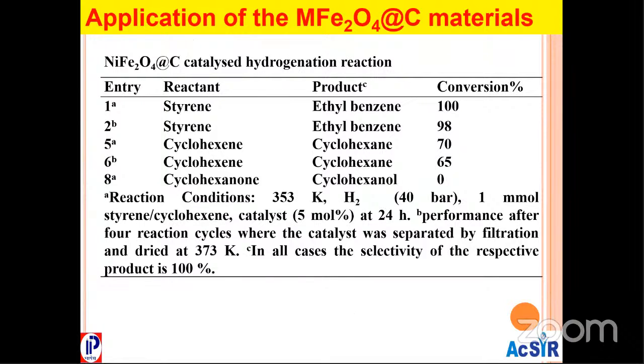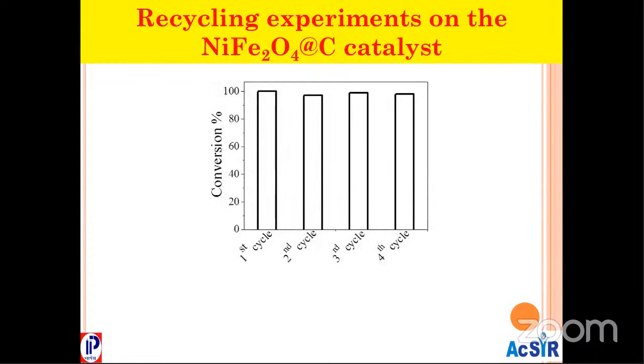So these are the other reactions. I have tried whether this catalyst can be used for other alkenes. For cyclohexene, it gave 70% conversion. For cyclohexanone, it gave 0%. So this material has special selectivity for that alkylated side chain, like for ethylbenzene. These are the recycling experiments. This material is stable up to 4 cycles.